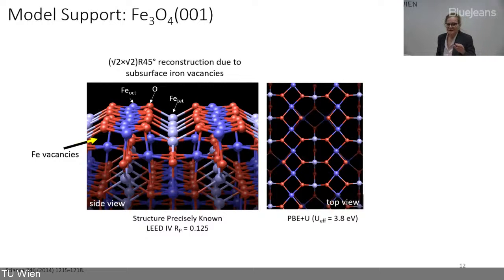The key thing, and that's why it took us a while to figure out what it is, is that underneath the surface there are well-ordered iron vacancies. Because of these iron vacancies, in top view you get special sites. Between two oxygen atoms, there's a special adsorption site. If you put a gold atom there, this is where it will stick.